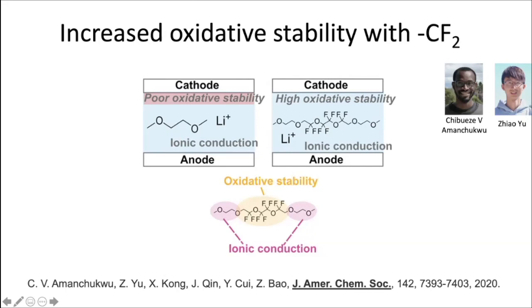And another aspect is the oxidative stability. The first one is lithium metal reactivity. The second one is oxidative stability. Here we made molecules that have fluorinated CF2 groups incorporated into the ether. This provides electron withdrawing capability. And then ethylene oxide units are substituted in for solvating the lithium ion and allowing transport of the lithium ion.